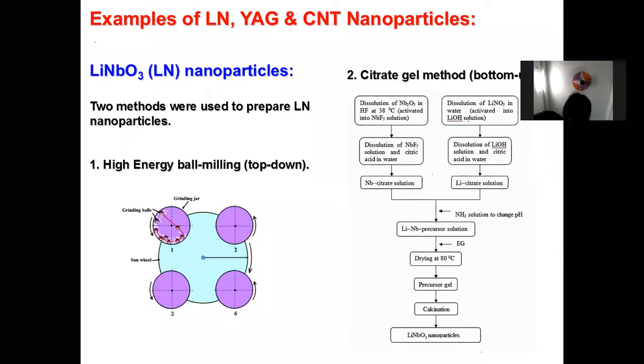First I will take the example of lithium niobate. Lithium niobate is basically a non-linear optical material. You can make NLO devices out of this material. It is very useful for making lasers. It is a laser host as well, but at the same time, it is a beautiful second harmonic generation material. If you have a laser in the IR, but you need that laser in green, you use this crystal, and the wavelength comes down to half. If it is 1064 nm, that is the Nd:YAG laser, it will become 532 nm, which is the green. So you can use that laser for other applications. You can use the red laser, you can use the green laser as well.